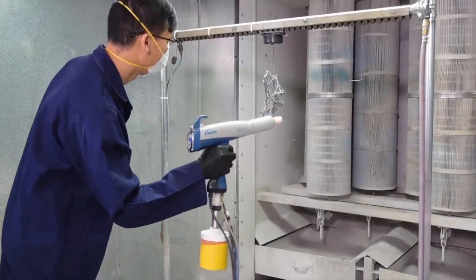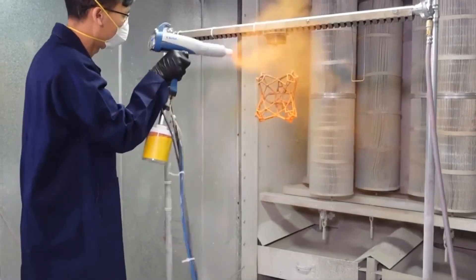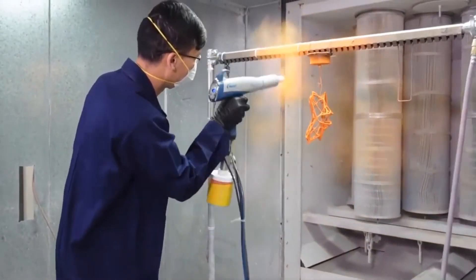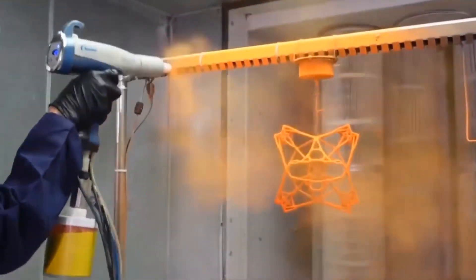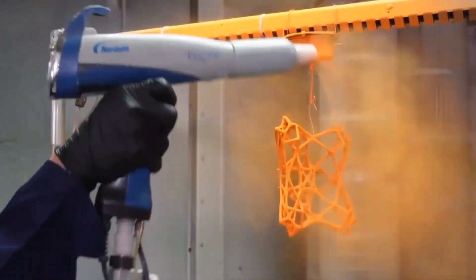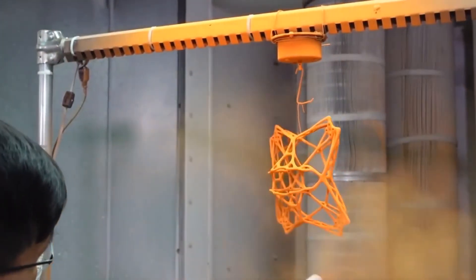UV cured powder coating is then applied electrostatically using a handheld spray gun. The powder forms a cloud that carries a charge. The charged powder is attracted to the grounded drone piece. He is ensuring an even layer of powder is applied to the part to obtain a coating thickness generally in the 2 to 3 mil range.